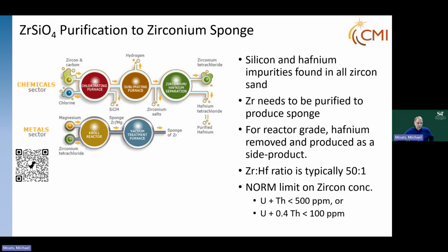The main thing when we look at zircon is you obviously have silicon impurity that you have to remove. We have to get rid of the silicon as part of the silicate. And then, if we're going to make nuclear grade zirconium, we need to get rid of the hafnium, which is about a 50-to-1 ratio. If you're not making reactor grade zirconium, then the hafnium doesn't have to be removed. It doesn't hurt your metallurgical properties. It doesn't hurt the corrosion aspects of it. So the only time hafnium needs to be removed is for nuclear grade materials.